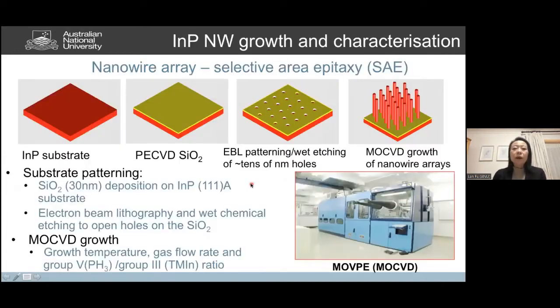So let me talk a little bit about nanowire array growth by selective area epitaxy. In this particular talk, I will mainly talk about our work on indium phosphide nanowire growth. In our group, we grow a variety of nanowire structures as well as nanomembranes and other nanoshapes, which I will not have time to cover in this talk. We normally start with an indium phosphide substrate, and we deposit a thin layer of silicon dioxide on top of that. Then we use electron beam lithography to design the nanowire array patterns based on our simulation work for different device applications. We combine that lithography with wet or dry chemical etching, so we can open nanometer-sized holes in the silicon dioxide, and then we put it into the MOCVD reactor to do the nanowire growth.